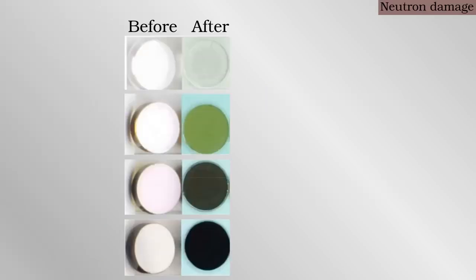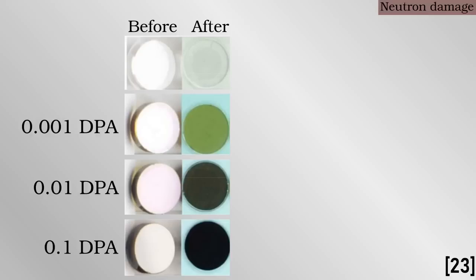To give an example, here is a study where mirrors were exposed to neutrons up to the levels of 0.001, 0.01 and 0.1 DPA, compared to a control without any exposure. As the neutron damage is increased, the mirrors become pitch black, and at the highest dose in this study the material has shrunk by over 2%. Granted, mirrors are generally very finicky and susceptible to damage. For most other components it doesn't matter if they end up looking scuffed as long as they do their job, but this gives an indication as to how much damage neutrons can do.